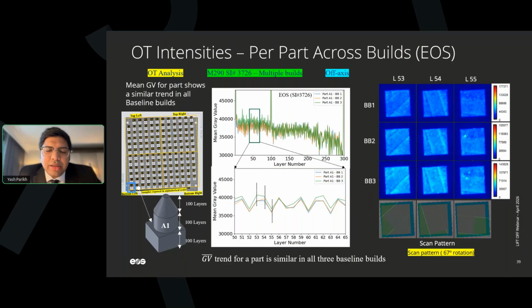On the top, you see all 300 samples. On the bottom is just focusing on the layers from 50 to 65. On the right hand side, you see layer numbers 53, 54, 55 for build job 1, 2, and 3. They have an absolutely different scanning pattern. It has a 67-degree rotation between each layer, so the three different build jobs have a different 67-degree rotation between them. That's how your infill is differing, and hence your emission of photons varies slightly. So that difference you can see in that plot. Go to the next one.